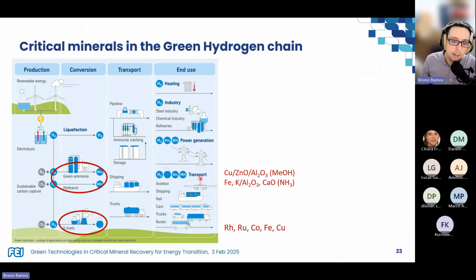So to make green ammonia and methanol, after, of course, obtaining hydrogen by electrolysis, we have to rely on these catalysts especially. So for methanol, the key catalyst is a compound of copper. It's comprised of zinc oxide, aluminum oxide, alumina, and copper metal. And to make ammonia, we normally use an iron catalyst and also potassium alumina catalyst and also calcium oxide.